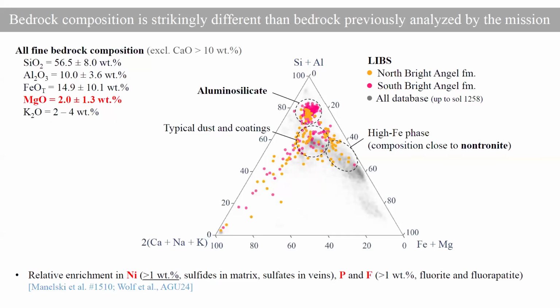Now, if we look at minor elements, and this is the work of Henry Manelski and Wolf, who have posters at LPSC this year, they also showed strong enrichment in nickel, up to 1 weight percent, which has never been measured to that level on Mars before. And also some phosphorus as well as fluorine enrichment, which is likely present as fluorapatites and fluorides.